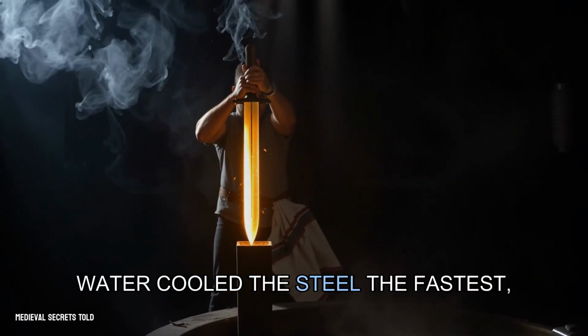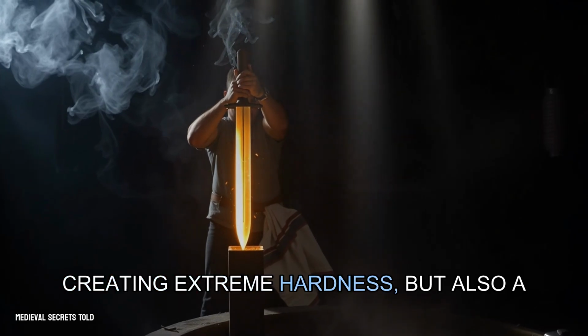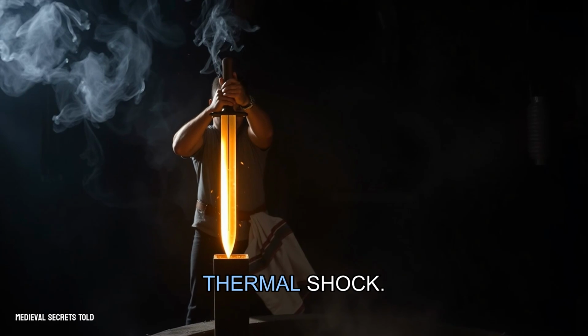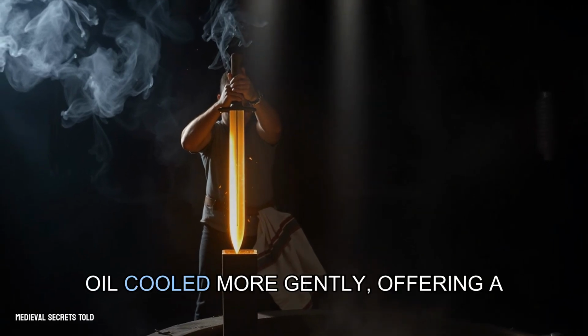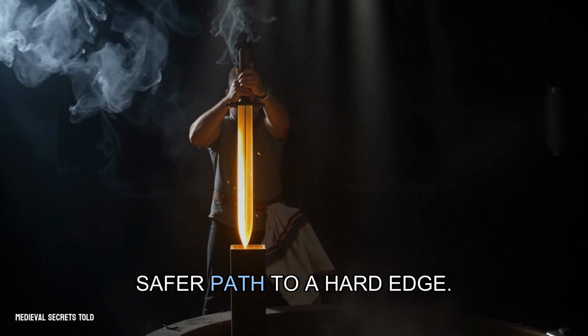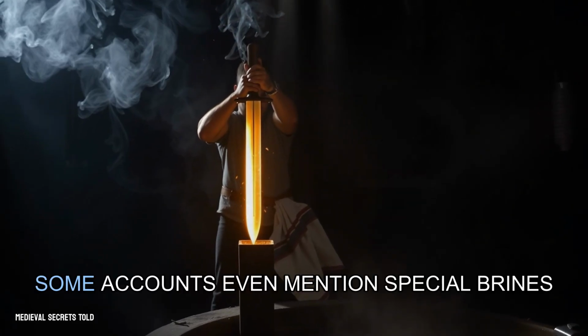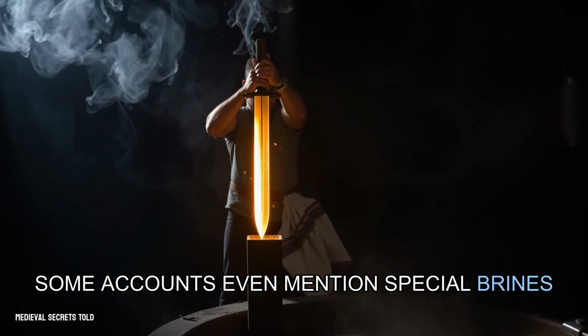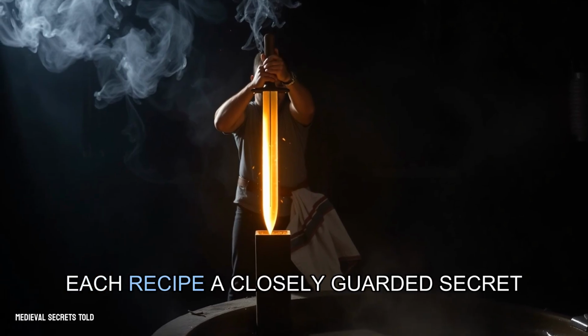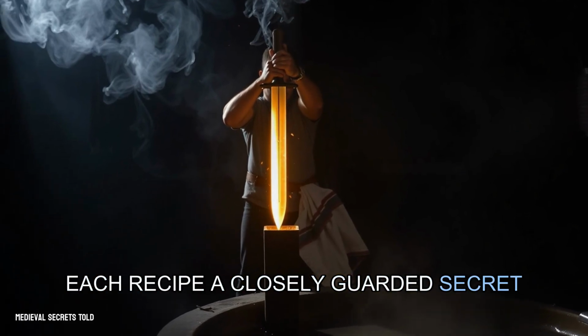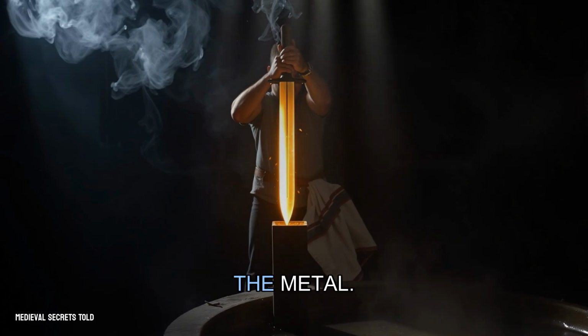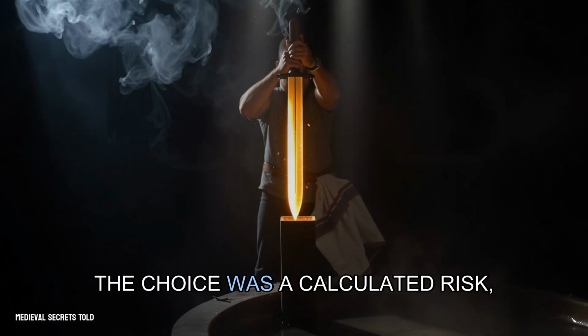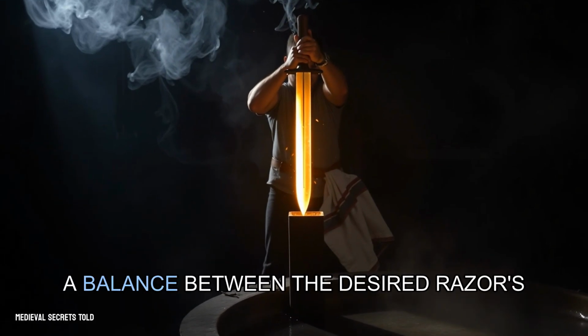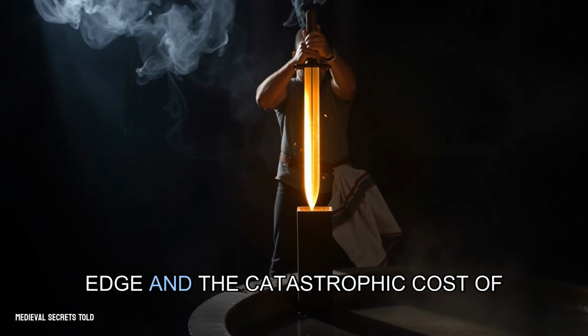Water cooled the steel the fastest, creating extreme hardness, but also a terrifying risk of cracking from the thermal shock. Oil cooled more gently, offering a safer path to a hard edge. Some accounts even mention special brines or other liquids, each recipe a closely guarded secret that altered the final character of the metal. The choice was a calculated risk, a balance between the desired razor's edge and the catastrophic cost